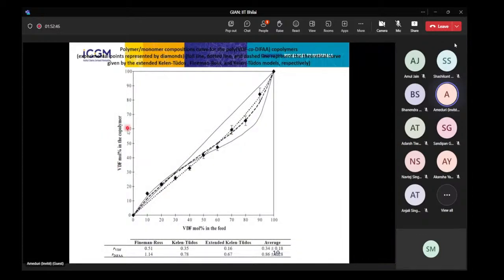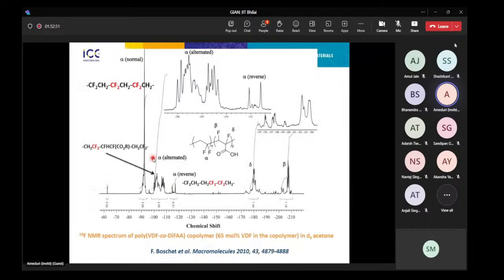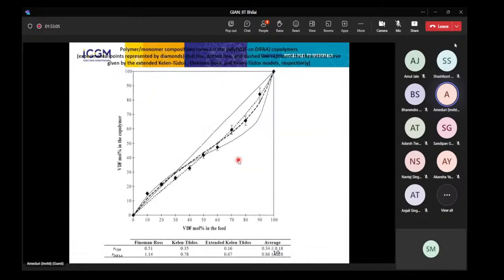And as you can see, we monitor variation by proton and fluorine NMR. So of course, with proton NMR, we are able to see the CH2 coming from VDF and also the CH coming from the difluoroacrylate. So just an example here, fluorine NMR, I don't show the proton NMR, but this is the calculation, and by different techniques of calculation, Fineman-Ross, Kelen-Tüdős, extended Kelen-Tüdős, it was possible to have an idea of the reactivity ratio. And indeed, we are not very far from a kind of ideal copolymerization in this case.